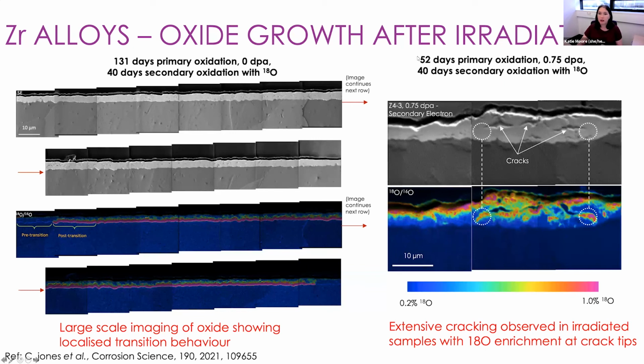So this alloy underwent a slightly shorter primary oxidation time. It was then sent to the Dalton Cumbrian facility, where Chris irradiated it with protons to an irradiation level of 0.75 displacements per atom. And then it went back into an autoclave containing oxygen-18 for another 40 days. So in this case, we can see the oxygen-18 is mainly on the outer surface. So the underlying oxide over here is still relatively protective.